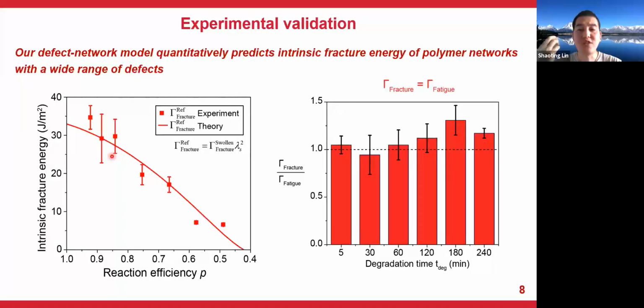As we show in the left plot, our model quantitatively captures the reported experimental results. One additional note we would like to highlight is that we find the fracture energy and the fatigue threshold of an ideal polymer network are the same. And even after introducing various densities of defects, its fracture energy and the fatigue threshold still remain approximately the same. This observation is also independent of the loading rate. We checked that this conclusion is valid at different loading rates. So this evidence further suggests the promising potential of using the material system to study other fundamental properties of softer materials.